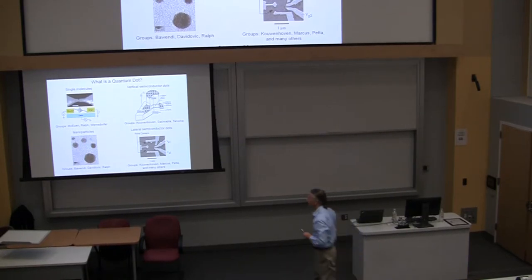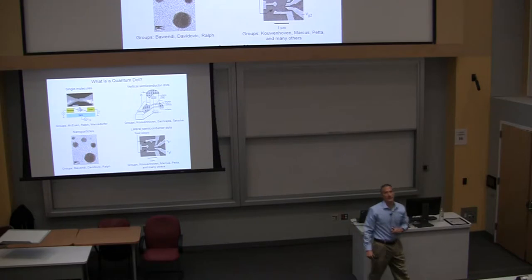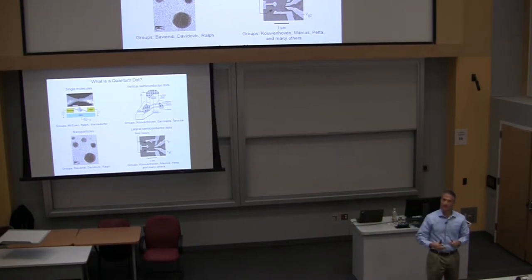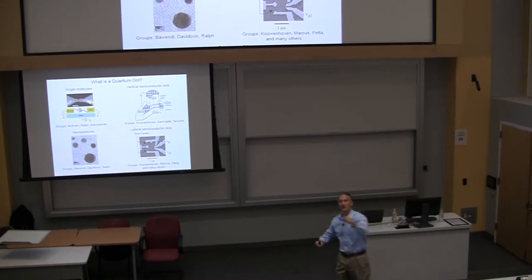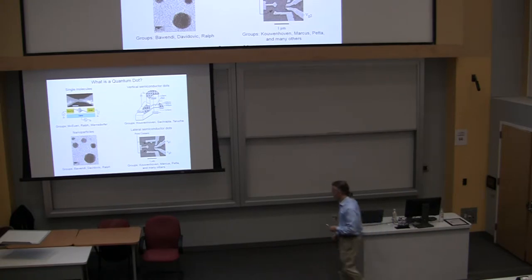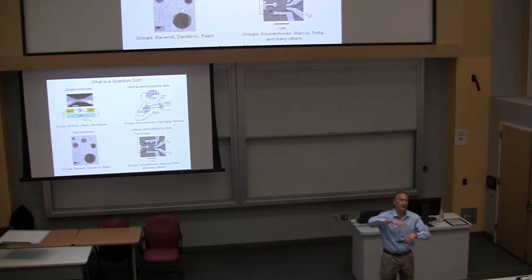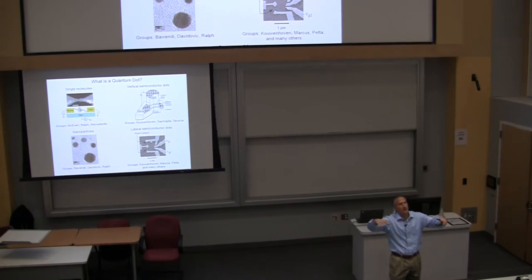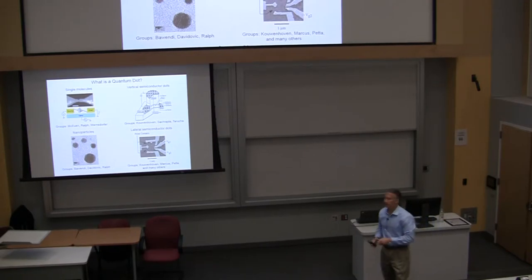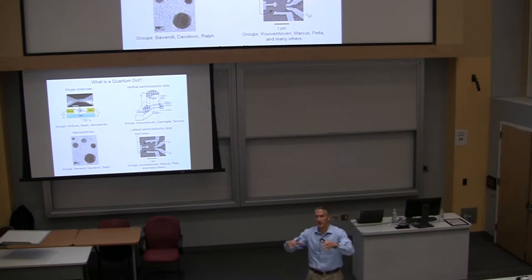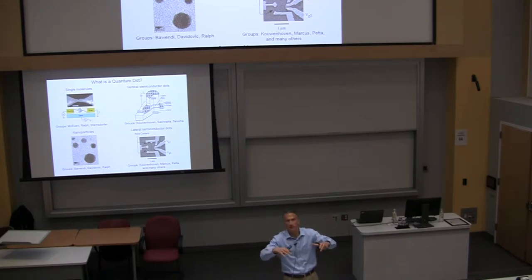Another example is the synthesis of cadmium selenide nanocrystals — there's a famous picture of test tubes full of nanoparticles of different colors based on their size, showing particle-in-a-box quantization in nanoparticles of metal or semiconductor. I'm going to focus on lateral quantum dots, where we use heterostructure growth to give electronic confinement in a plane. Then, to control confinement in the other two spatial dimensions, we use lithographically defined gate electrodes to push electrons around and build a cage around them. The quantum well gives confinement in z, and the gate electrodes give confinement in the XY plane.